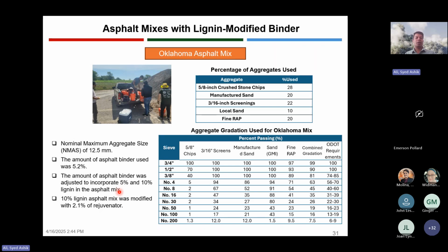At Oklahoma, we also tried another thing. We had seen some issues with the performance of the lignin modified binder. So we wanted to see whether the use of a rejuvenator can help improve some of the properties that we had issues with. So we used 2.1% rejuvenator on the 10% lignin modified asphalt binder mixes.